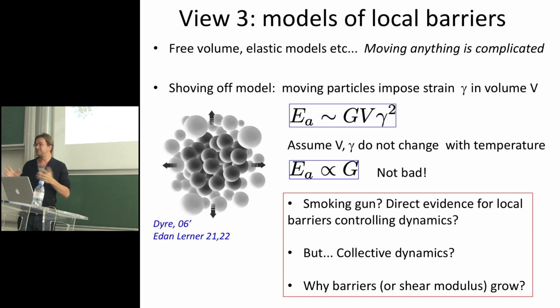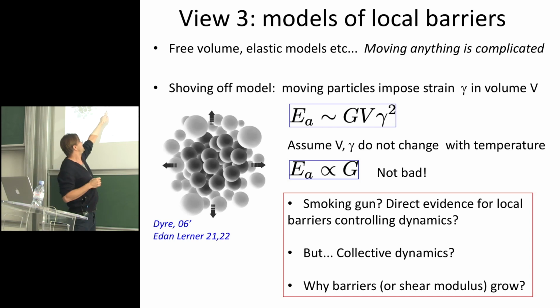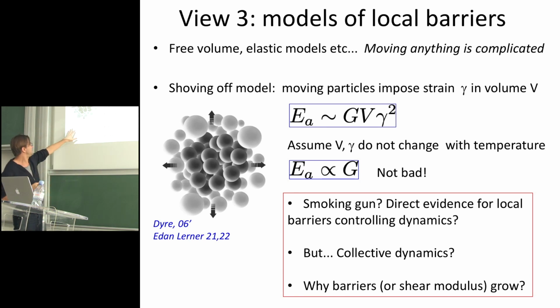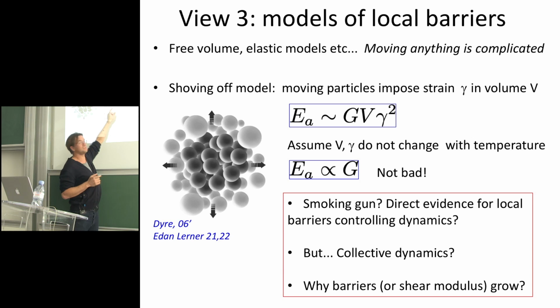And then just from elasticity, you expect that this will cost you some energy that will grow like the elastic modulus times the volume times the strain squared, something like this. Okay, so it's a very simple estimate. And then if you make the non-trivial assumption that this little volume V and the little strain gamma do not change with temperature, then you would predict that the activation energy would grow with the shear modulus in the system. And now there are more refined pictures of that, like Edan Lerner in Amsterdam. Now it's true that those two quantities appear to be quite correlated. So fragile liquids are also liquids that get quite stiffer under cooling.